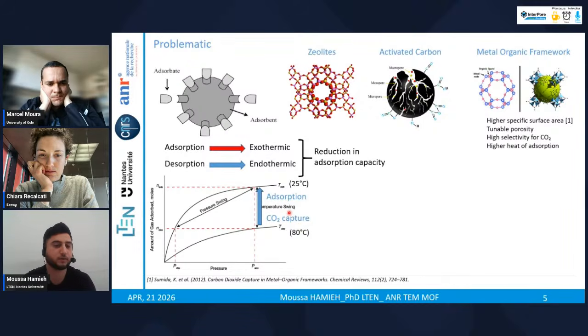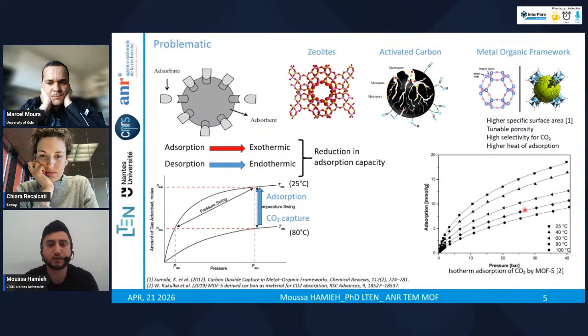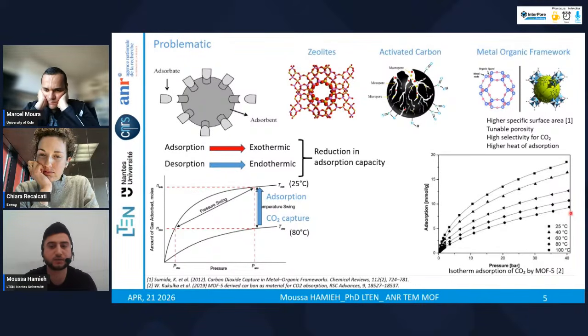It will be the inverse during the desorption. We want to heat, so during the desorption, the MOF will be cooled down, so it will move from one isotherm to another with lower temperature, and the MOF will be likely to adsorb instead of desorb the CO2. So these thermal effects are not at all negligible, because as we see here in this reference, we have the isotherm lines of CO2 uptake for the MOF-5, from 25 degrees to 100 degrees. We see, for example, at 25 degrees we have an adsorption capacity of 17 millimole per gram. And with heating the sample, for example at 80 or at 100, we have at the end about 7 to 9. So here we are losing about 50% of the adsorption capacity of the MOF. And this is not at all negligible.